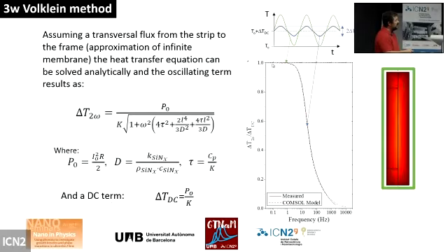If we do a sweep and a spectral analysis of the delta T 2 omega versus delta T DC, we can also extract the heat capacity of the film from that information. But for the experiment where we wanted to measure the thermal conductance in real time, we had to fix the frequency at that point, because there we were able to extract the delta T DC, the same magnitude that Völklein was using from DC measurements, from the AC measurement.